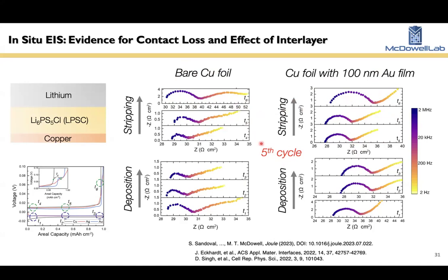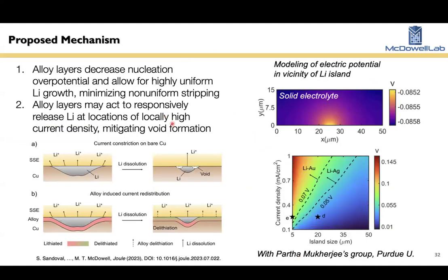So basically, we think there are two factors. These interlayers are allowing for nucleation and growth that occurs in a different way, and there's much more uniform lithium growth across the interface, which is useful. The interlayers also help to retain contact at the very end of stripping, which allows for much better cycling and prevents, at least initially, filament formation. And there's a model here that was also developed to explore this in more detail. There's some evidence that there's potentially release of lithium from these layers as well, which can help mitigate some of the voiding issues.